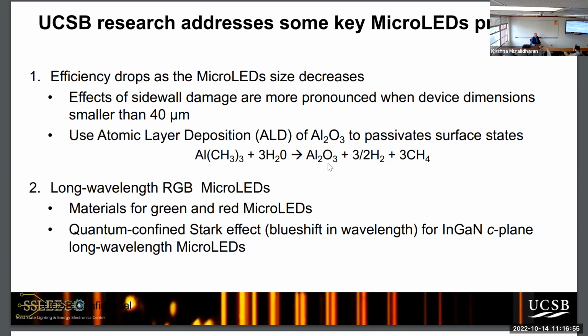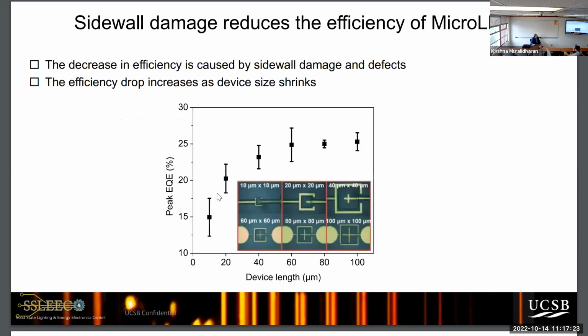So ALD is a very important tool, not just for gallium nitride, but all silicon processing now uses this chemical reaction or version of this chemical reaction. So you could see my career is basically involved in material science, but also chemical engineering. And then we do the electrical engineering on the structure. And what we found out, aluminum oxide gave us the best passivation. We'll see how it affects the devices. And it also lets us now get to all three colors of red, green, and blue. So here's the problem: when you go from the 100 micron to 10, efficiency dropped from 25 to less than 15. And so this is the problem we're trying to solve.